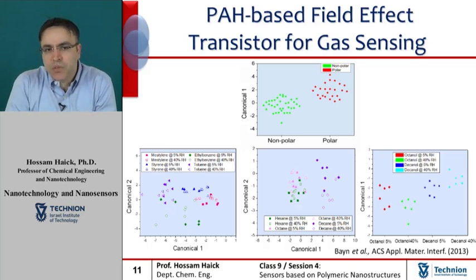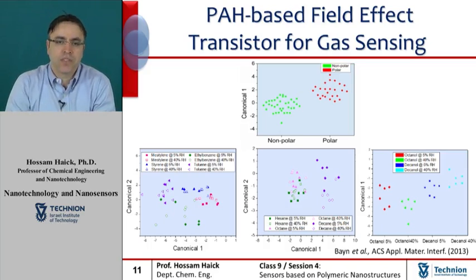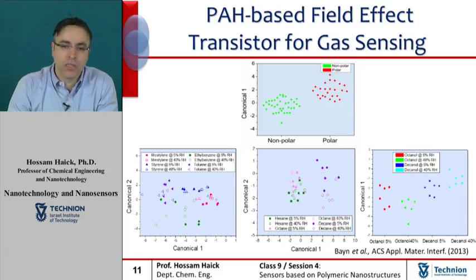Altogether, these results demonstrate the viability of the PAH-based field effect transistors for volatile organic compound sensing applications in humid atmospheres. The ability to extract multiple electrical features as well as multiple signal features from each PAH-based field effect transistor provides a reservoir of sensing signal that allows discrimination between aromatic and non-aromatic volatile organic compounds, discrimination between polar and non-polar aromatic compounds, and identification of specific volatile organic compounds within the subgroups at both low and high relative humidity levels.